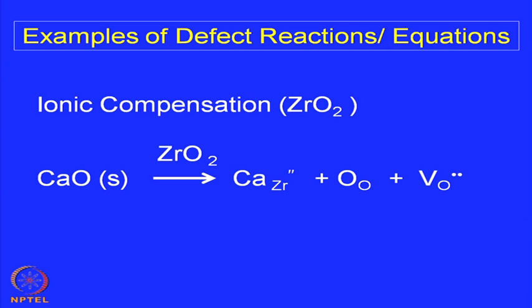Zirconia, as you know, has 3 different polymorphs, and to stabilize the highest polymorph, the cubic polymorph, you have to add some other divalent metal oxides like calcium oxide. Sometimes trivalent metal oxides are also added, like yttrium oxide. By adding it, there is what is called the aliovalent substitution. That means zirconium 4 plus has been substituted by calcium 2 plus.